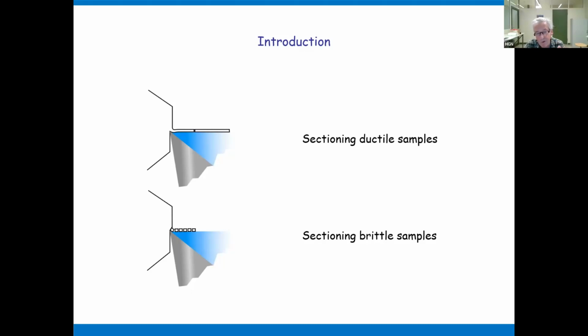I'm used to work with hard materials like diamond, and then if it comes to biological material, it is not really hard, it is brittle. And that's the situation when you section a ductile material like an epoxy resin. The sections are lifted up to the water surface and swim. They are stretched to a certain extent, not completely. There is compression left, but they are stretched. If the sample is brittle, like maybe the bone, at least the non-decalcified bone, the sample tends to break.